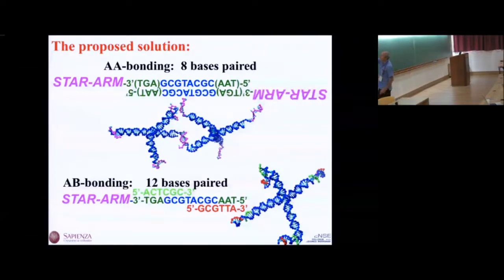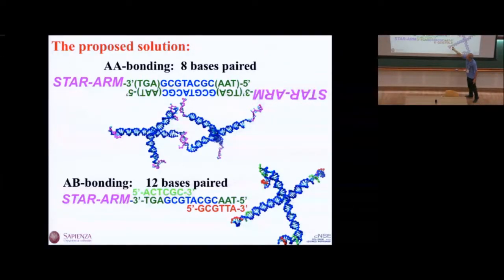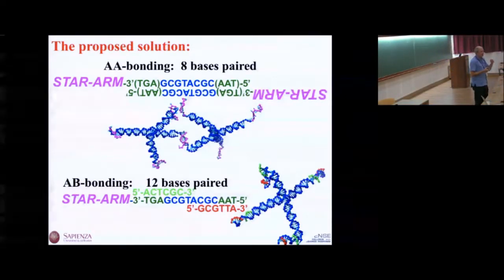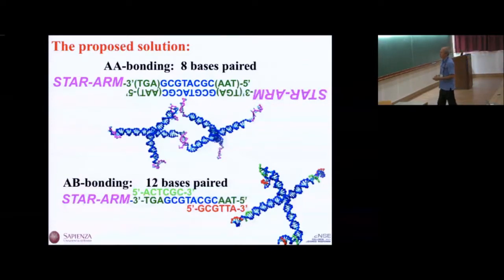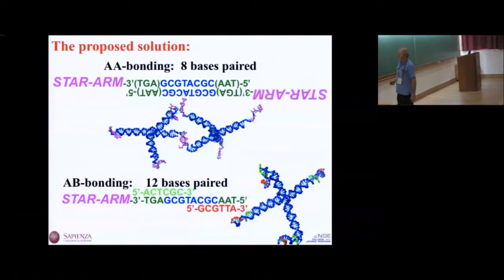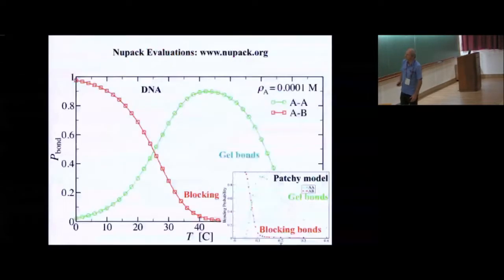And this is graphically shown here. So I have 2 pieces attached, one here and one there. So I created my isolated nanostar. So this idea of splitting the capping sequence in 2 parts also adds an additional amount of entropy, which was what we wanted, right? Because now we have to freeze the center of mass of 2 particles to create the bond. So it's even more entropically costly. So this is good because this destabilizes this binding, and only at low temperature this will take place.